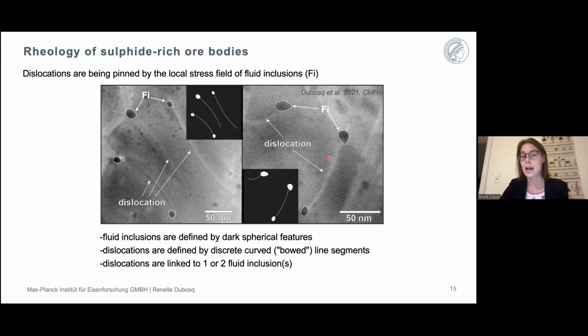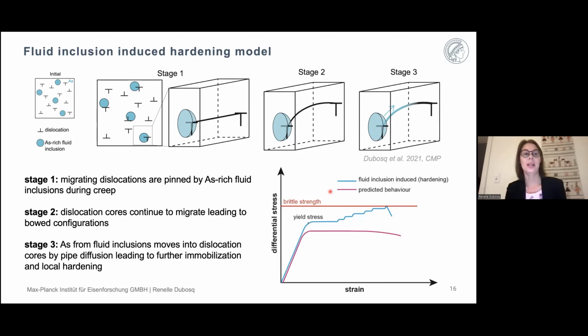And they also appear to have a bright contrast in the STEM images, suggesting there is a segregation of the heavy element in them. So based on these observations, I came up with a new fluid inclusion induced hardening model. So in the first stage of this model, dislocations migrate during creep processes, and they then become pinned by arsenic-enriched fluid inclusions as they encounter them. In the second stage, the portion of the dislocation in between the pinning points can continue to migrate during creep, which is what leads to the bowed or scalloped configurations that we documented in STEM.